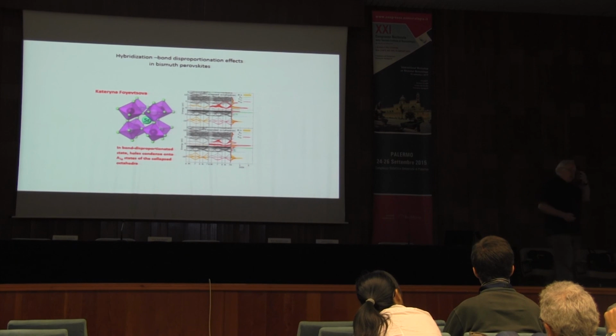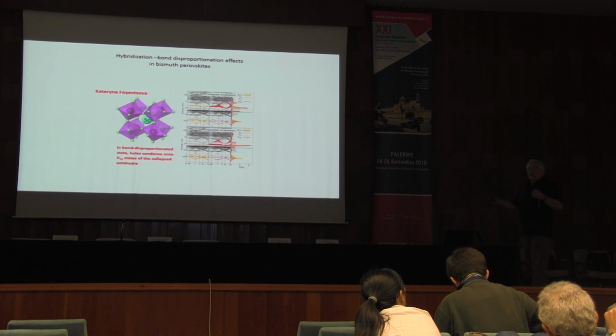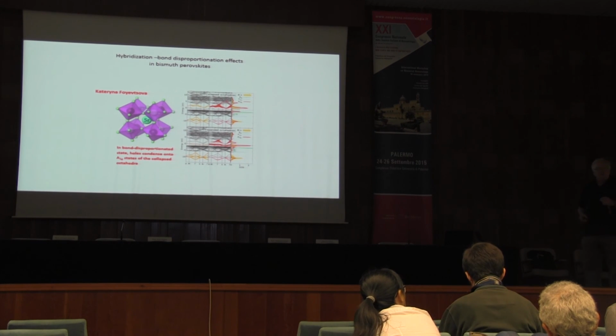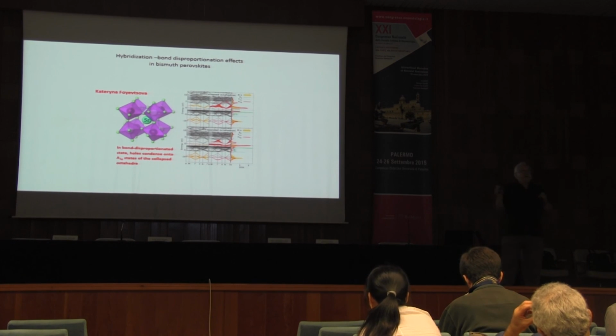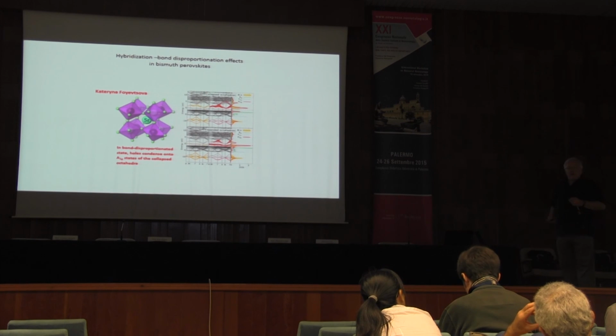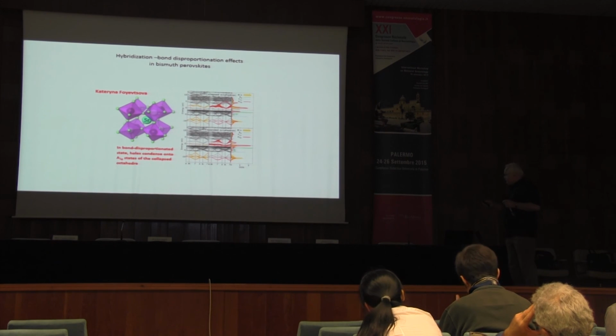Okay. Now, this is the competing phase for superconductivity. What you have to do is get rid of that order, just like you have to get rid of the magnetic order in the cuprates in order to get superconductivity. In many cases, you have these competing orders. You have to get rid of the one that competes with the superconductivity in order to get superconductivity. And somehow or other, and we don't know exactly how that works, this is done by potassium substitution. And when you substitute potassium, you start emptying up this band here.